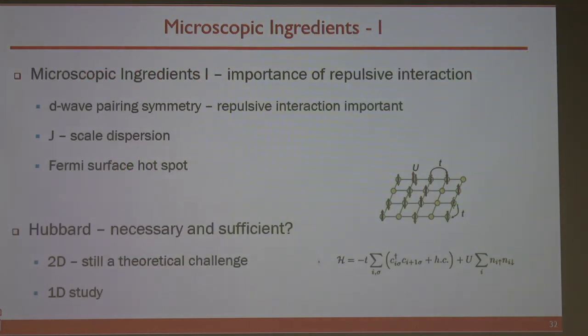Okay. Now, this, of course, tells you something about d-wave pairing, which is unconventional. Now we have evidence to believe the antiferromagnetism did quite a bit on the electronic structure. It's telling you this physics of magnetism, of J, is very important. So that naturally leads to this kind of physics of the Hubbard model. So it leads to what I said earlier: is the high temperature superconductivity in cuprates equivalent to the physics of the Hubbard model?